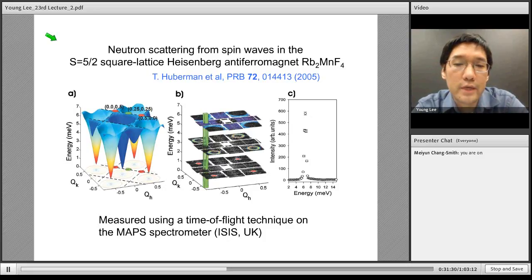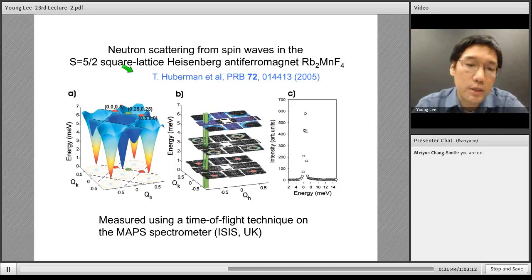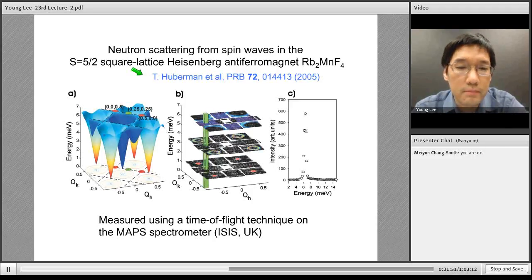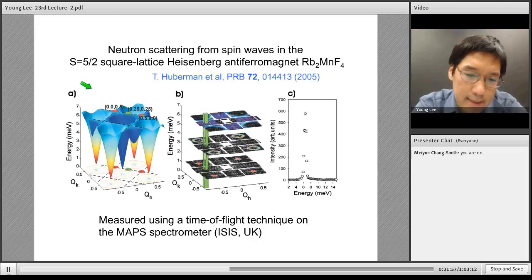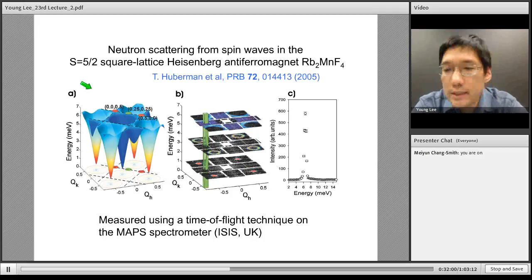Here's some neutron scattering data on a spin 5/2, so relatively large spin, square lattice, Heisenberg antiferromagnet, rubidium manganese fluoride. Manganese is the magnetic ion here. This was work done by Huberman and Roger Cowley's group, and some people from Bob Birgeneau's group at MIT, who I knew. They did these measurements at ISIS in Rutherford Lab in England using the MAPS spectrometer.